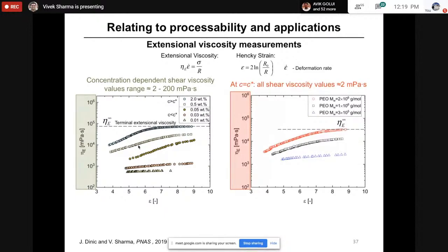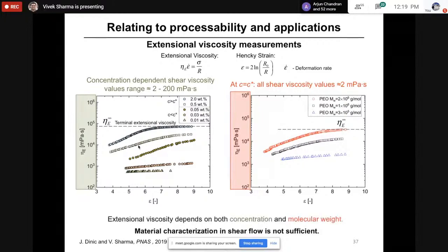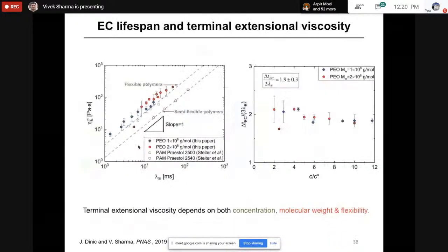If we take different molecular weight polymers all at C star, all these 3 different molecular weights will have the same shear viscosity, just 2 times water viscosity. However, the extensional viscosity is orders of magnitude apart. And this tells you how changing molecular weight can really influence your drop formation dynamics, dispensing behavior, and so on. But the key takeaway from all my presentation is material characterization in shear flow is not sufficient, especially for dispensing applications. It's important to characterize the extensional response.